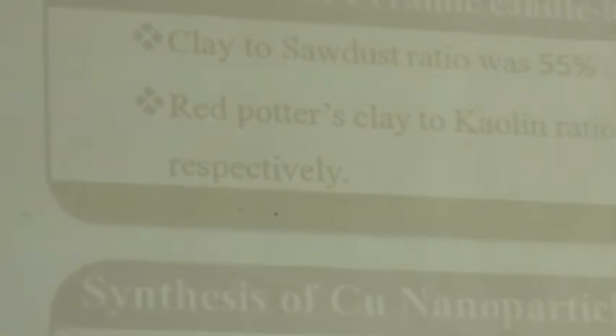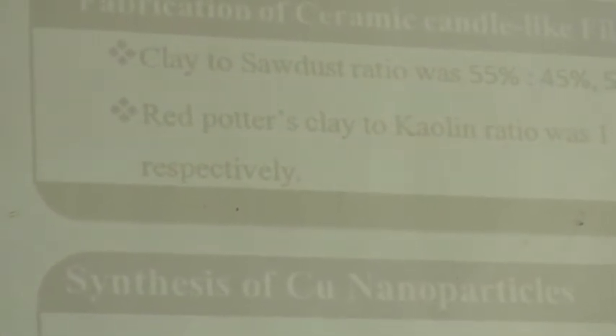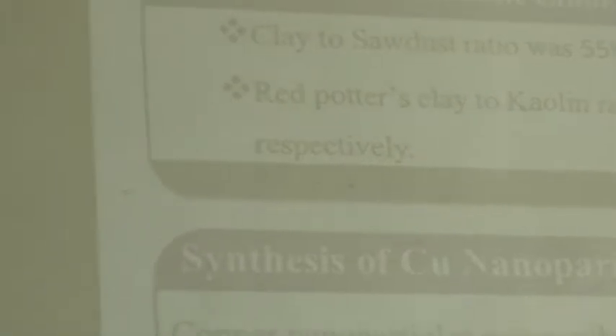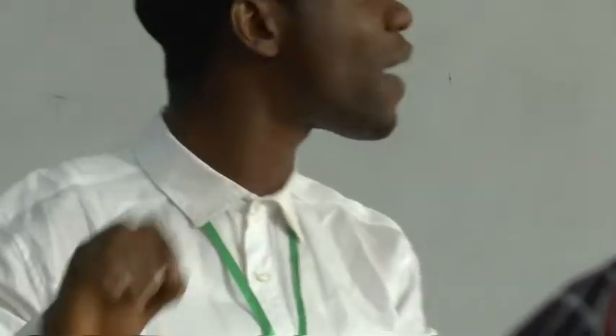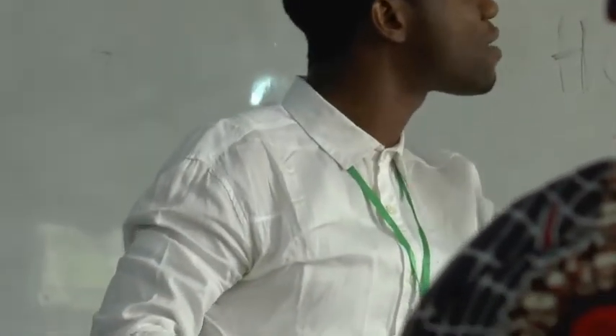Methodology. Fabrication of the ceramic candle-like filter. The red potter's clay, the white kaolin clay, and the sawdust were collected, pulverized, then sieved to the finest particle sizes. Then the ceramic candle-like filters were fabricated by varying the volume composition of the clay, that is red clay and white clay, to sawdust in the ratio 55-45, 50-50, and 45-55%, while the ratio of red clay to white clay is 1:1, 2:1, and 1:2 respectively.